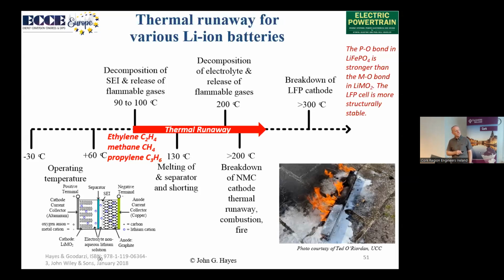We have gases, we have heat. At about 200 degrees, the electrolyte really starts to break down, and we're going to get increased release of flammable gases. Now for that nickel, manganese, cobalt, somewhere over 200 degrees, that's going to break down. And the secret of that is that it has the O2 in there. So now we release oxygen to meet up with the heat and the combustible gases,